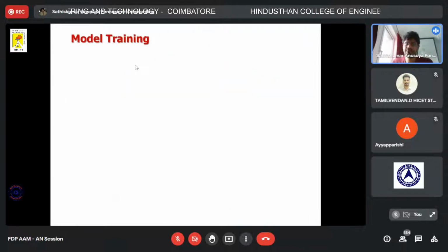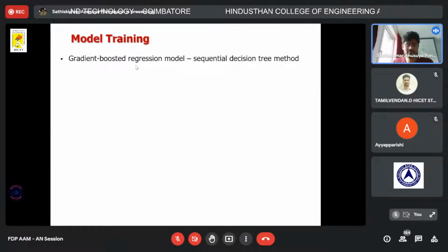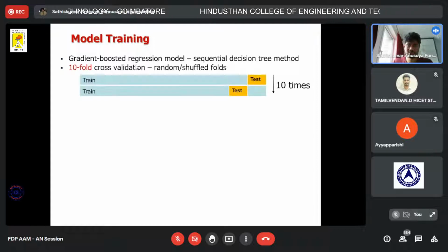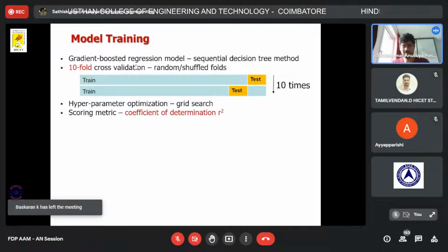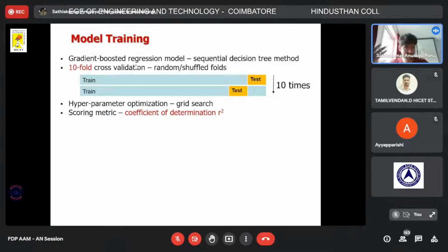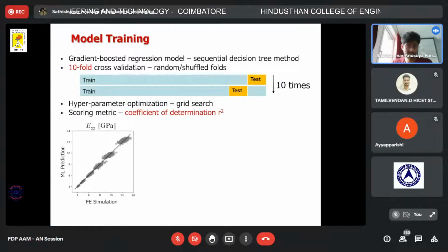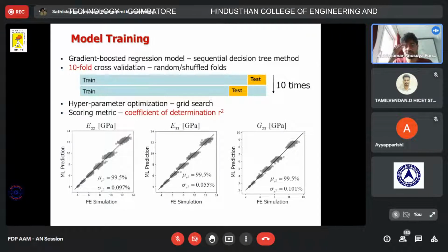And then we go to the actual machine learning model, which is a gradient boosted regression model. We use so-called tenfold cross-validation, which is a way to generalize your model and test its accuracy. And after a set of hyperparameter tuning, meaning optimizing your machine learning model for better learning, you have the results. Once your model is trained, you have the results, as you can see in the bottom.